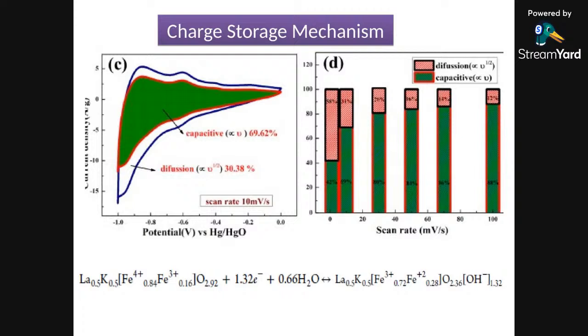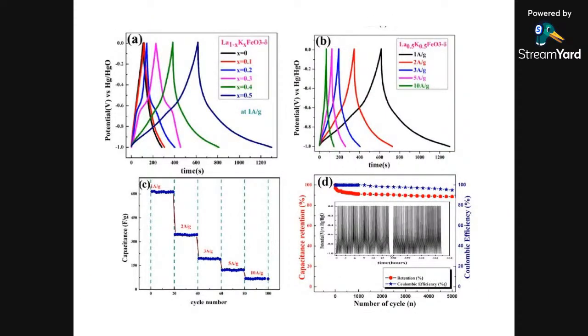So even using this lanthanum FeO3 cell, we can get this storage. Interconversion is a very favorable mechanism in perovskite materials. That's what we have found, and now a lot of work is going in that direction to make an alternative to activated carbon, because a lot of work is going on active transition metal ion pseudocapacitor electrodes. So the combination of these two can give us an aqueous battery-kind-of material, with battery-kind-of storage, and we may be able to generate very high charge storage and power capability using the cell made of the potassium cations and the LaFeO3-based anions.